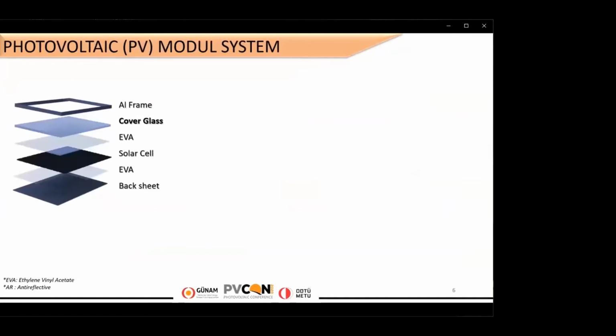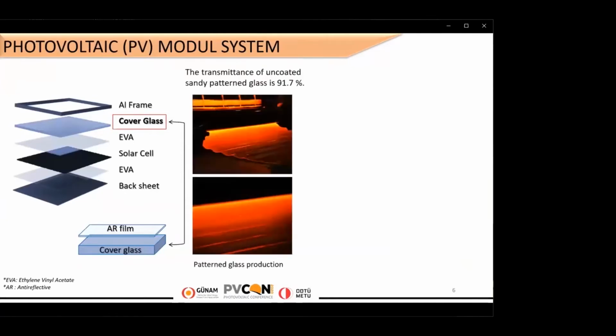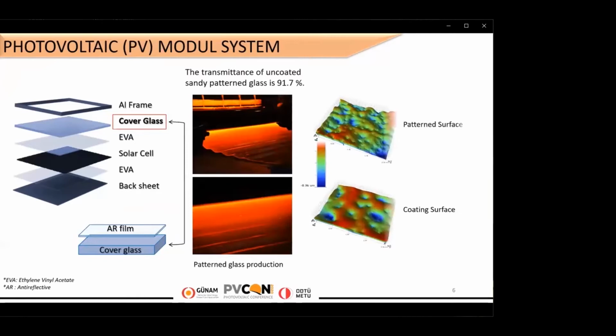You can see all layers of the PV panel system. The cover glass is what we are interested in, because the anti-reflective film will be applied on this layer. I also want to talk about the production of Şişecam cover glass. As a substrate, we used pattern glass, and you can see pictures of glass on the production band. The hot glass is shaped while passing between two rolls, one with a pattern and the other without pattern. We applied AR film on the surface without pattern.